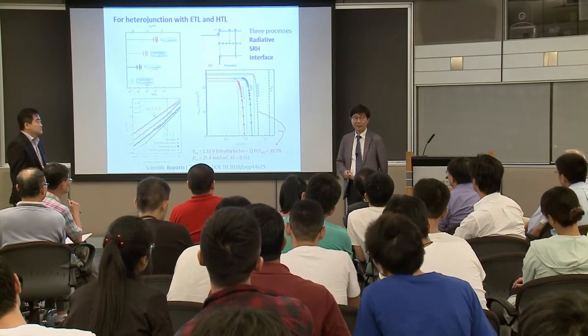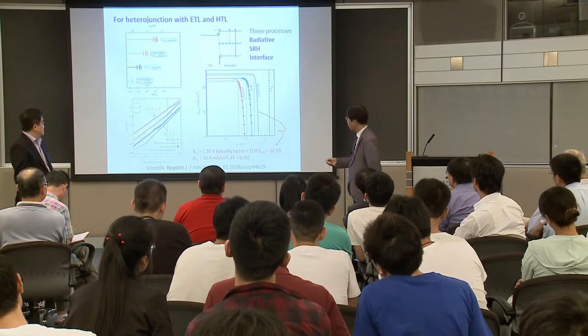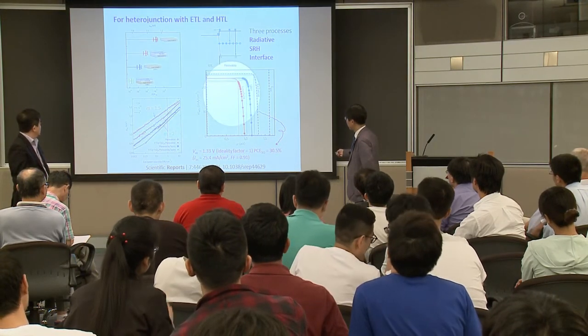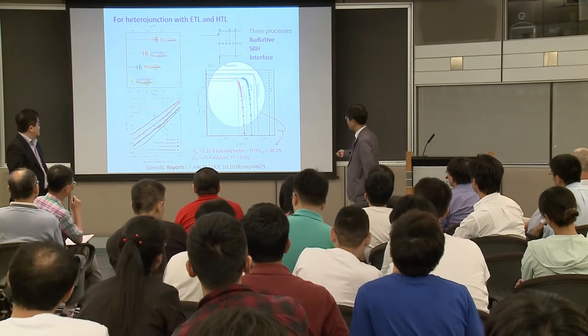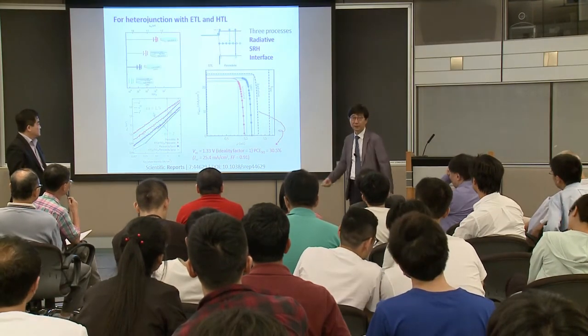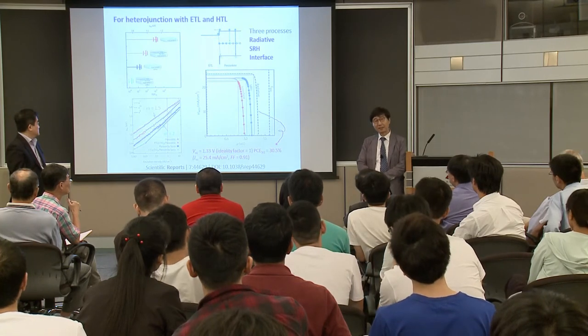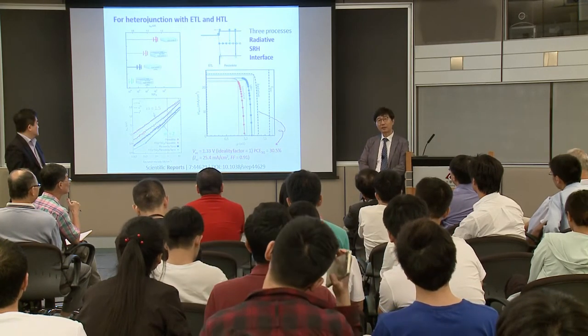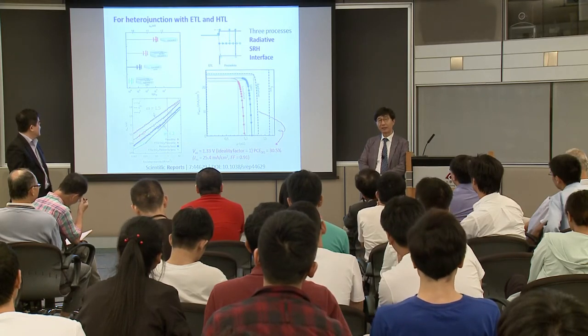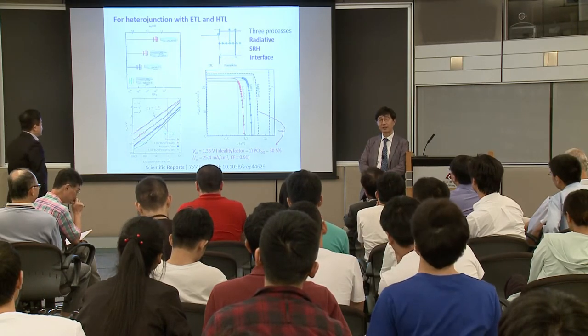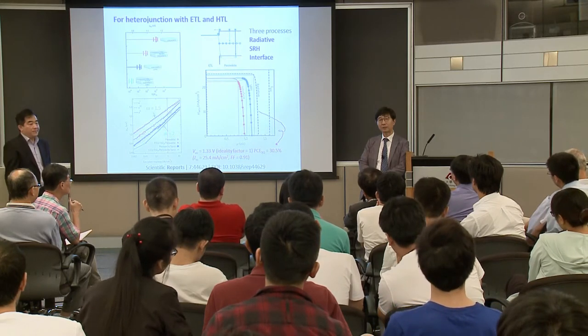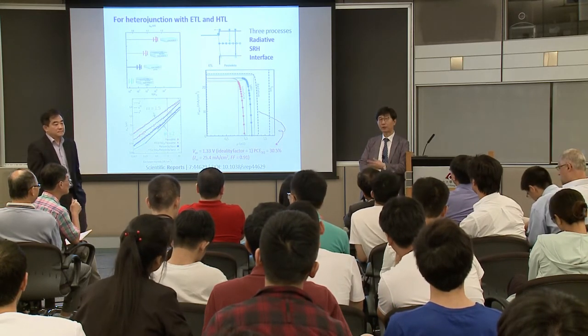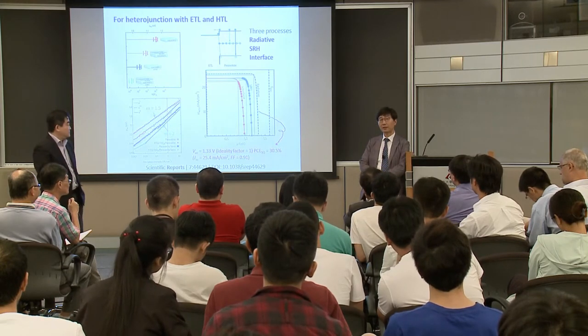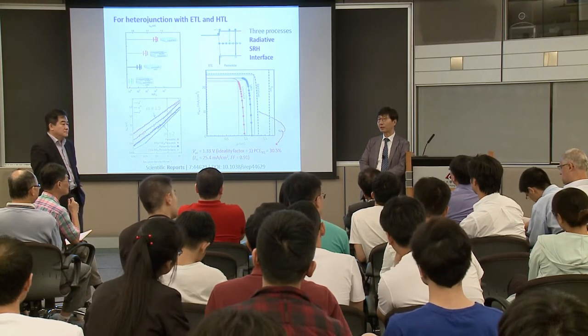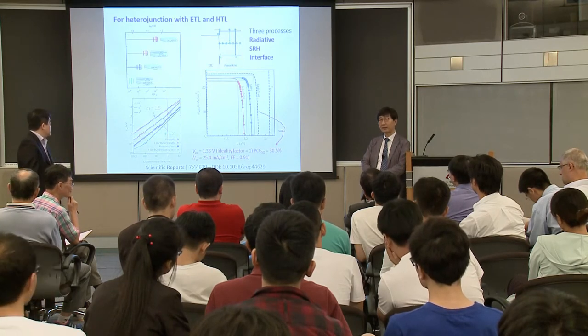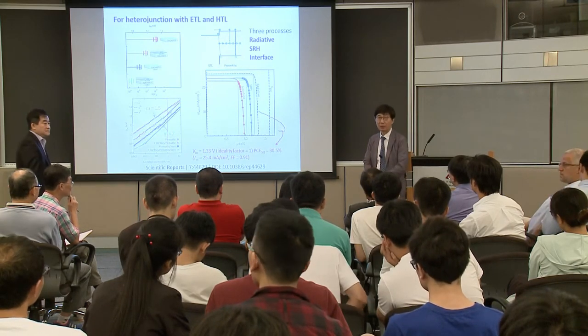We cannot judge it right now. Probably the SRH and also interface, but I think the interface recombination is dominant, compared to SRH. If we think about the defect tolerant property of perovskite, then the interface recombination is more critical than the SRH recombination. This is my opinion.